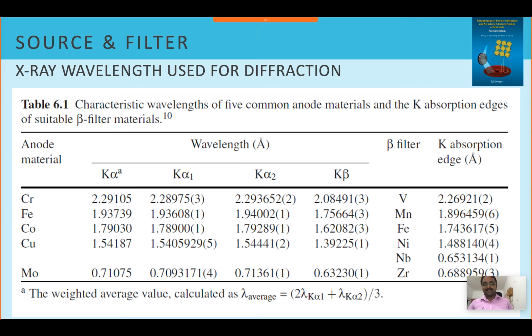So in this diffraction you can see copper. For example, if on copper we are going to incident high energy electrons, you will get a wavelength of K alpha as 1.54187 and K alpha 1 as 1.5405 and K alpha 2 as 1.5441. We should know the difference between these things, and K beta. So this is the second major wavelength coming out.